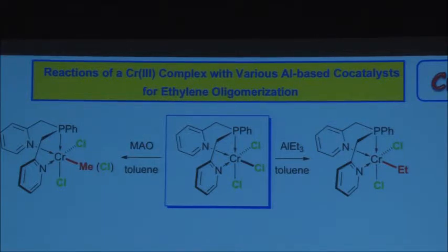So we always have to be cautious. I'm not saying that there is complete conversion, but at least that compound was formed. If you take now methyl aluminum oxane, which is the famous MAO, you replace partly this chloride with a methyl from methyl aluminum MAO, but there is a disorder, crystallographic disorder, so there is still some chloride here. So in both cases, these catalysts have operated as alkylation catalysts. They've alkylated the metal center.